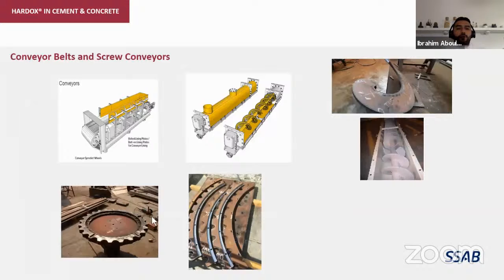Next slide, please. Conveyor belts and screw conveyors. Usually in the screw conveyors and the conveyor belts, they are rubber, but they are relined with steel plates. And for that, like I said, it's sliding wear, completely straight sliding wear. So more or less, Hardox 600 can be used without any problem, since you don't have any impact problems in that case.